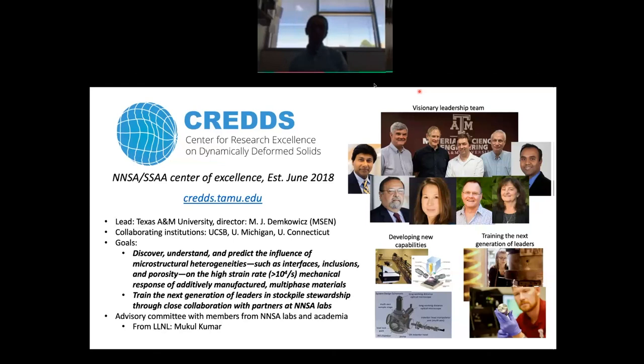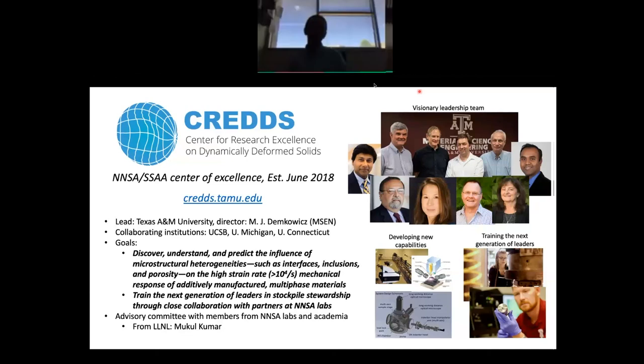So we also have a question from Lauren Benedict, who asks, in your vignette number 2, did you perform detailed interfacial free energy calculations with the molecular dynamics to obtain the interfacial free energies that you then used to parameterize the phase field model? Or did you grab the interfacial free energies from somewhere else? Thanks. Well, we did not calculate the free energies. We calculated enthalpies. So we calculated interface enthalpies, and we used those to parameterize the phase field model.